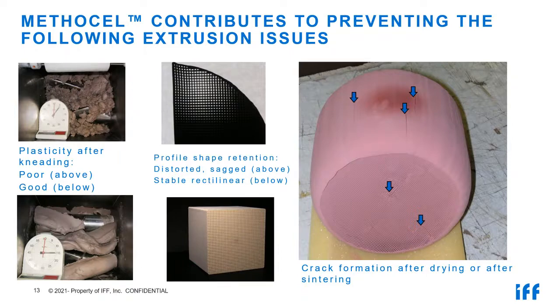Now we are coming to a major issue, crack formation. I'm quite sure there's nobody here in the line who never saw crack formation during extrusion. It can happen at many places, and it can have many reasons. In some cases, the right choice of METHOCEL can really help and can solve a problem, even if the METHOCEL is not the reason for it.